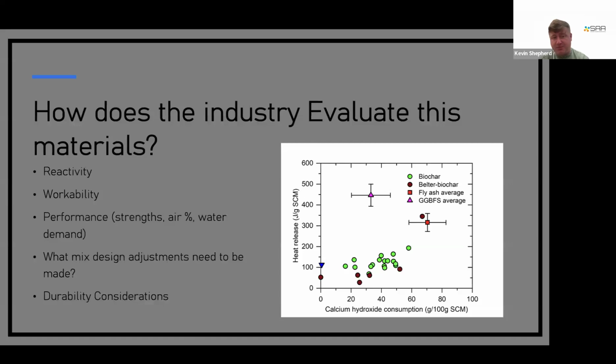And a lot of people will ask, well, how do we evaluate biochar into materials or into concrete? The first thing I like to take a look at, again, a lot of people will probably have different opinions, but I take a look at the reactivity with the University of Miami. There's a modified R3 method that they use that can give me the calcium hydroxide consumption in 72 hours. And that pretty much shows the heat release, right?